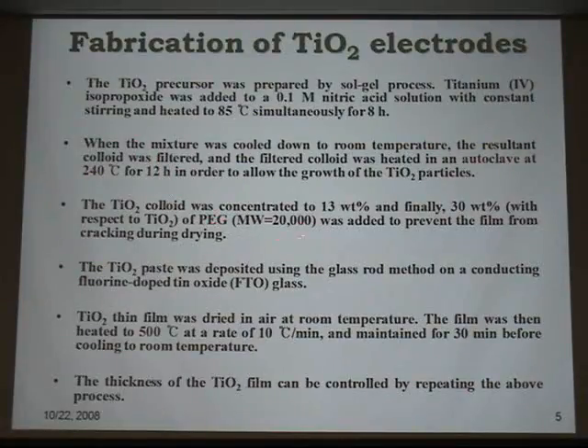And you add some polymer to the precursor before you heat it up to a certain temperature. The purpose of this polymer is to suspend those colloids, so that you can later burn off the polymer and create a micropore or mesopore structure. And this step is also very critical in order to get enough surface area with the right pore size.